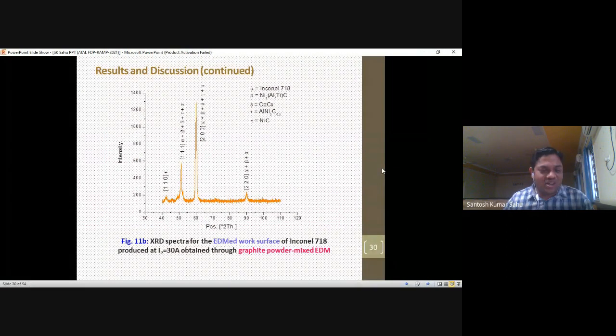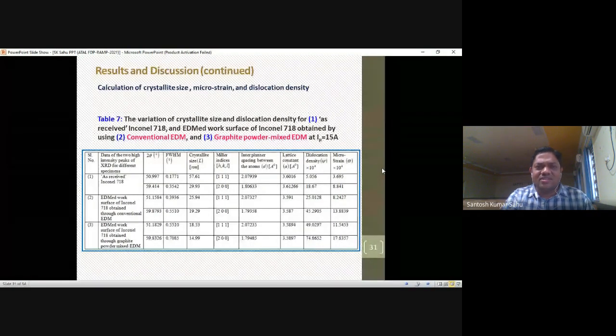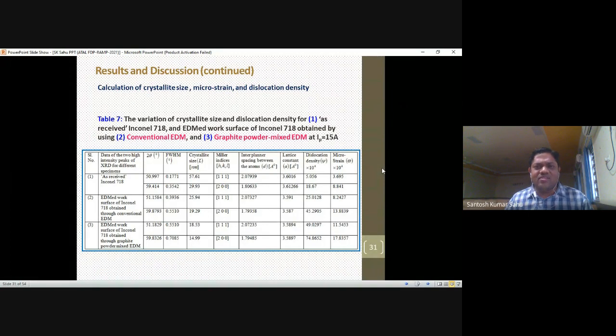Already we have discussed this part. Again, in powder mixed EDM, some amount of residual stress is also released due to the mechanical abrasion effect of the powder particles on the surface, and therefore crack formation is remarkably reduced in powder mixed EDM, and you get a refined specimen also. We can calculate the crystallite size, microstrain and dislocation density.